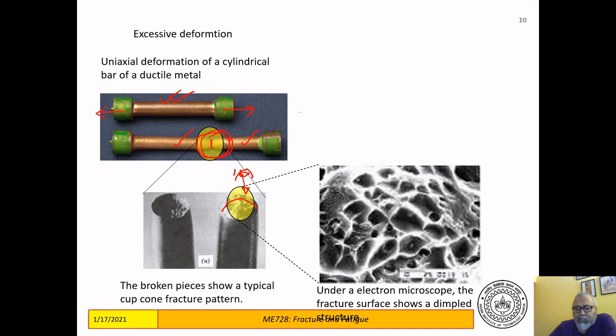So this is a ductile material, steel, aluminum, copper, and this is a typical close-up of a cup and cone fracture. If you looked at the cone, and if you looked at the cup, you would see more or less a similar kind of picture. Now, people have looked at these. These are actually signs of early defects that caused the failure.